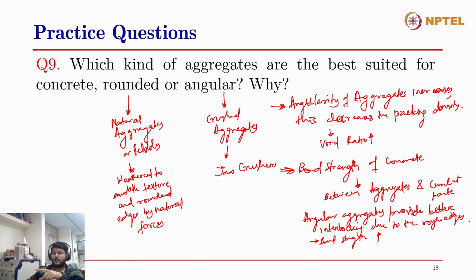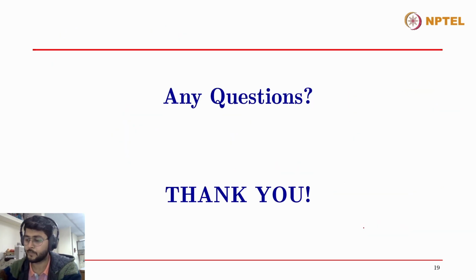On the other hand, if you want a higher bond strength when you use rounded aggregate concrete, you have to mix it with certain angular aggregates, or else you'll have to use those kinds of aggregates which have a rough texture. Rough texture aggregates also allow for better bonding. The smooth texture of aggregates compromises the bond strength of the concrete. So this answers the last question.